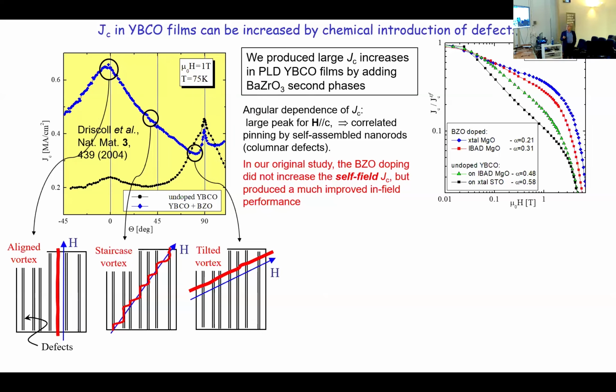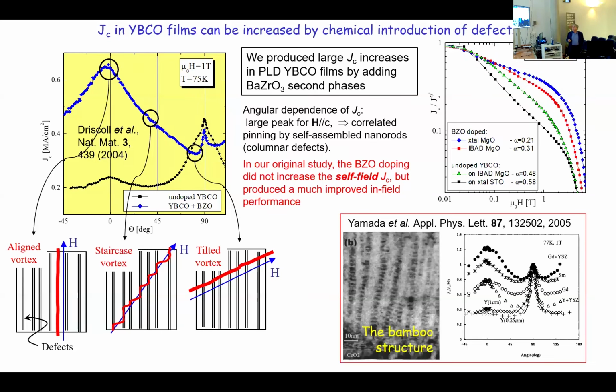And those nanorods act as columnar defects. So they produce very strong pinning. The nanorods were parallel to the z-axis. You have seen this sketch before, but these are nanorods produced chemically, not by heavy ion irradiation, but the physics is the same. And what we observed in that original study is that we didn't see a big increase in self-field JC, but we saw a very strong improvement of the in-field performance that was essentially what we were looking for. This was quickly reproduced by other groups like the Yamada group, and they had this beautiful TEM showing the self-assembled nanorods.